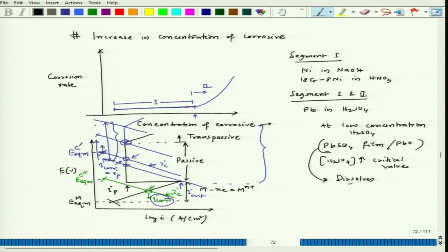So that means the bare metal surface is exposed and the material corrosion rate further increases, and sometimes it becomes an exponential rise. That particular pattern is observed in the case of lead pipe, let us say a lead pipe carrying H2SO4. At a low concentration, it can maintain a low corrosion rate, but at a high concentration, lead becomes highly soluble. Okay, corrosion rate further increases. So these two patterns can be observed in the case of lead, starting from low concentration of H2SO4 to